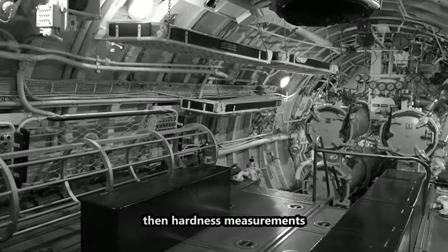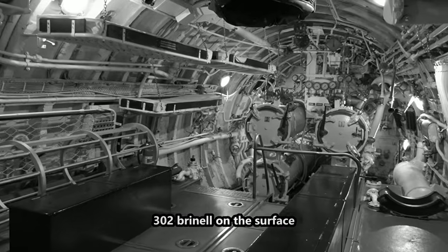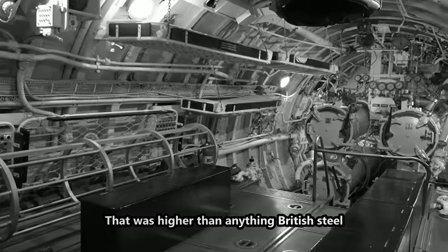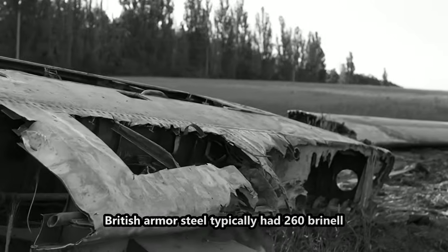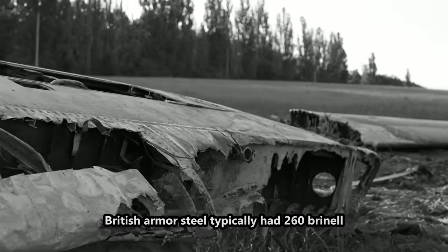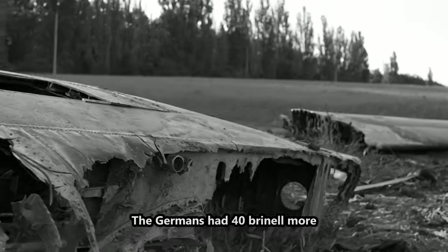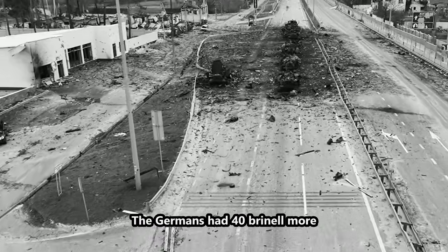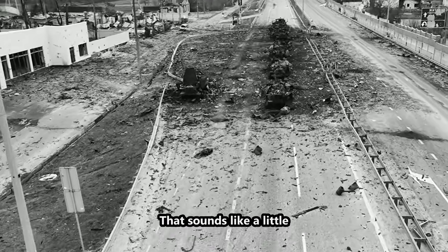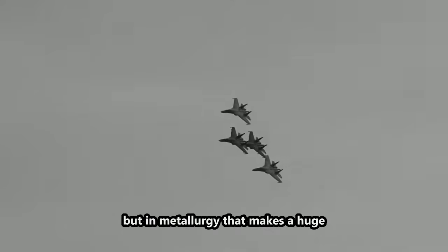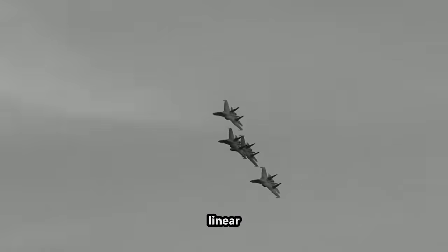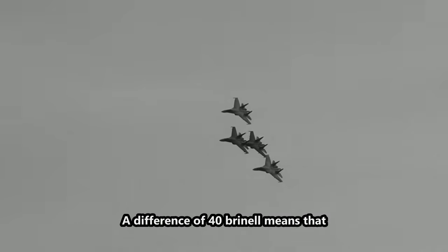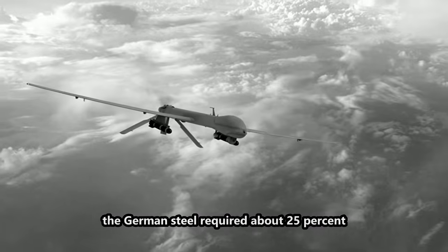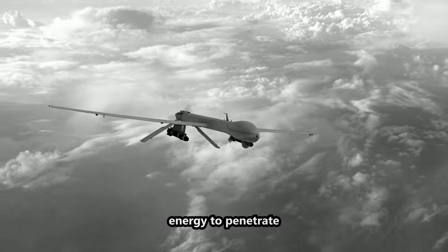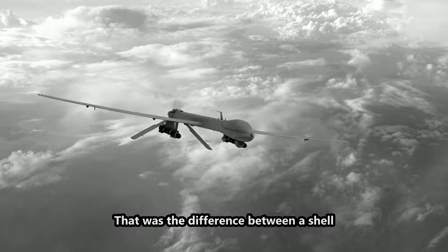Then, hardness measurements. 302 Brinell on the surface. That was higher than anything British steel achieved. British armor steel typically had 260 Brinell. The Germans had 40 Brinell more. That sounds like a little, but in metallurgy that makes a huge difference. Hardness scales are not linear. A difference of 40 Brinell means that the German steel required about 25% more energy to penetrate. That was the difference between a shell that bounced off and one that pierced through.